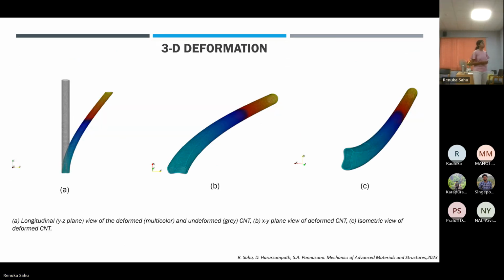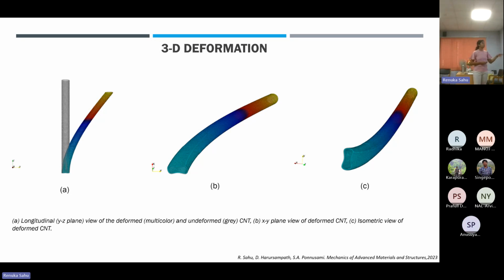We also captured the 3D deformations for the CNT in this case, where the gray model represents the undeformed CNT, and you can see the transverse deflection once the bending and compression has taken place. Here it's clearly seen that there is an ovalized, dumbbell-shaped nonlinear cross-section of the CNT.